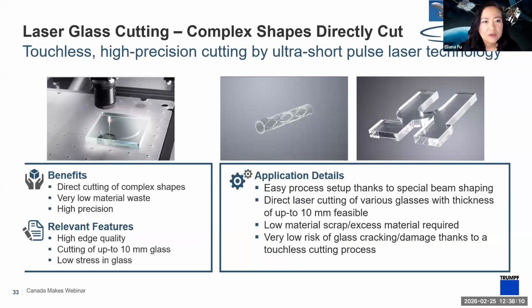We can also look at precision cutting with the ultrashort pulse laser on things like glass. So glass, you think is a pretty difficult thing to cut, but you can use a laser on it and it has a kind of no contact, no tool contact, an easy process to set up. And then you basically just tell the laser where to go and you can directly cut thickness up to 10 millimeters feasible. And because you're using a laser and not a tool, you have a very low risk of cracking and damage because it is a touchless process. So you're not inducing stress into that process. So it's very handy for things like that.